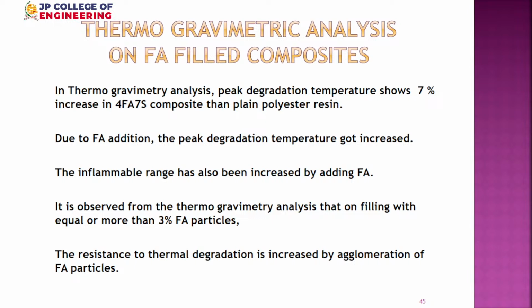Okay, so therefore, you can say that the fly ash composite shows a 30% improvement in degradation temperature. That is good. In particular, even 3% of particles gives better thermal stability. Next slide, please.